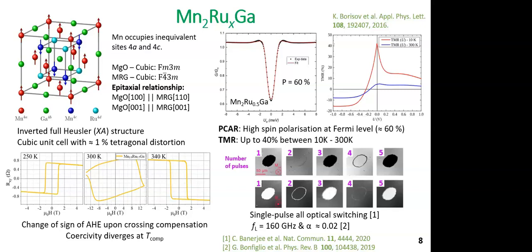And another thing that should be noted is that after we cross compensation, the anomalous Hall effect coefficient changes sign, which is another indication of compensation. And what we find is that the compensation temperature increases with increasing ruthenium content in MRG thin films.